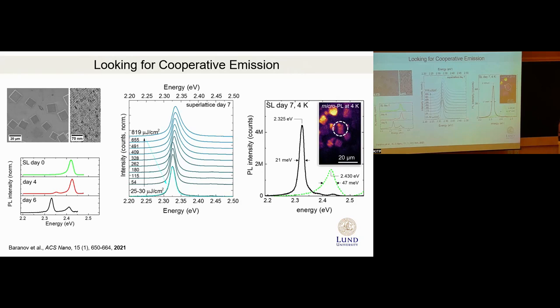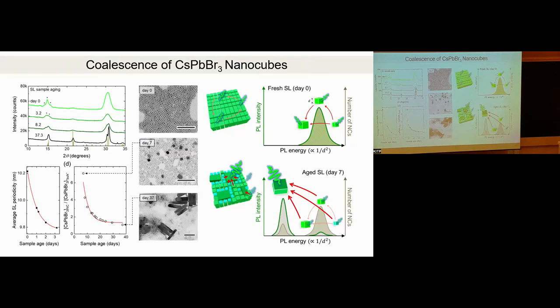So we tried to measure it as a function of power. Again, in this case the sample was more stable, and the explanation for this peak, which we came up with, was unfortunately more trivial. What happens is that nanoparticles start coalescing inside the superlattice over those days. After a week, you essentially have a mixture of small nanocrystals with large band gaps and large nanocrystals with small band gaps. There is energy transfer going on, and that's why you have this secondary emission. This is one of the key differences: our choice of sample synthesis and the different surface passivation resulted in these effects, not the ones which, for example, other groups saw.